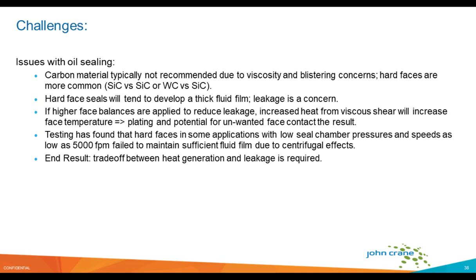So typically, from a material perspective, most seal designers and suppliers would like to utilize carbon for at least one of the seal faces, because carbon tends to wear in and have good lubricating properties, and also tends to provide the lowest leakage. When we're talking about an oil sealing application such as this, typically the viscosity is too high for carbon, even an antimony-filled carbon, so we run into the possibility of blistering and causing damage to the carbon. And so then we have to look at alternative materials, which would be typical hard faces like silicon carbide versus silicon carbide, or tungsten carbide versus silicon carbide.